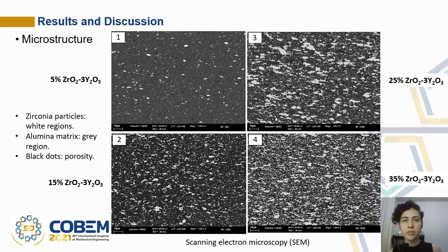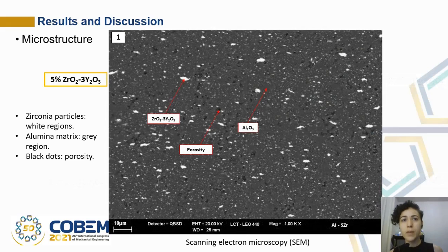The figure below shows the SEM images taken from the sintered samples. The white regions are fine zirconia particles, the gray region is the alumina matrix, while the black dots are porosity. In the figure, we note that zirconia particles are evenly distributed throughout the alumina matrix in all samples, indicating that the mixing step provides homogeneous powder. In this figure, we observe porosity dispersed throughout the sample, but as the zirconia content is increased, the porosity is reduced, as we can see in this sequence of figures.